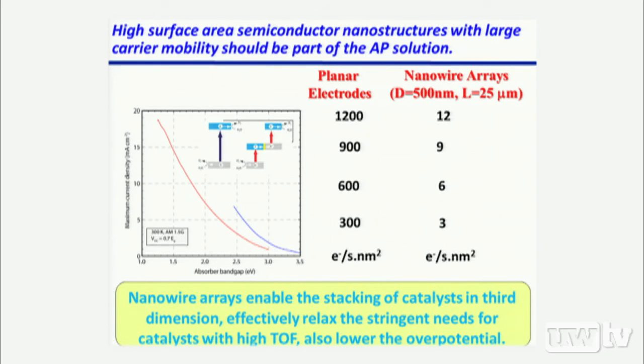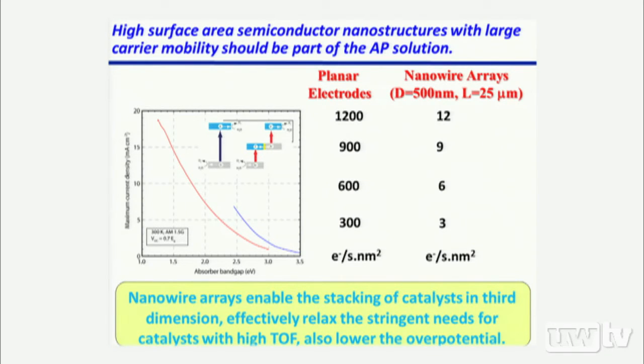It's very hard to find a water oxidation catalyst and a CO2 reduction catalyst with that high turnover frequency. But now if you turn everything into high surface area electrodes, from planar electrodes to a nanowire array, by increasing surface area, you have the capability to stack the catalyst along the Z direction. You can immediately reduce that to, for example, 6 electrons every second over 1 nanometer square. And that's durable. That's a durable target for water reduction. Of course, for water oxidation and CO2 reduction, we are still far off from that target. But that's a reasonable target, given that we are utilizing high surface area semiconductor electrodes.